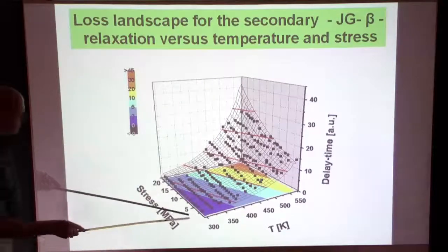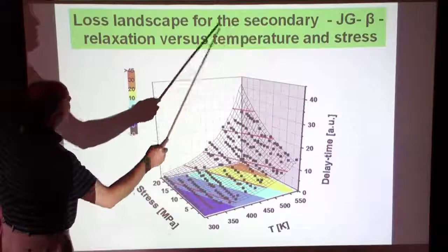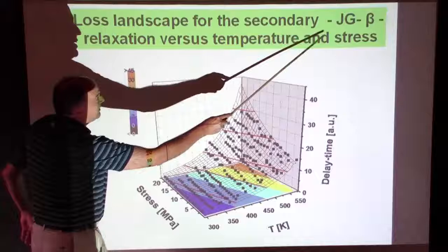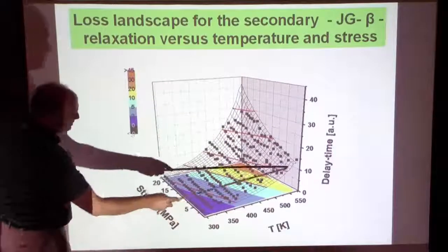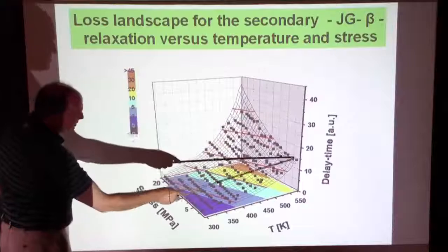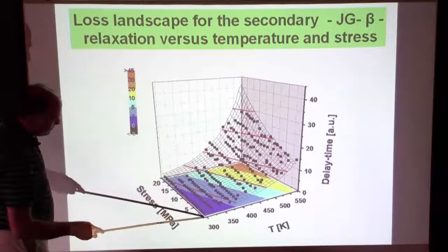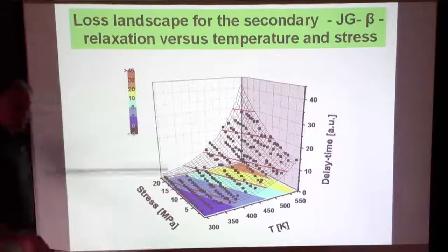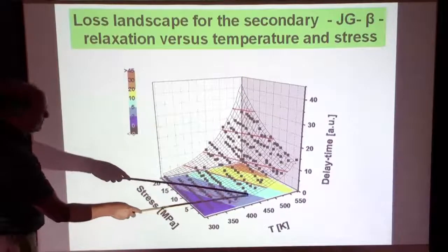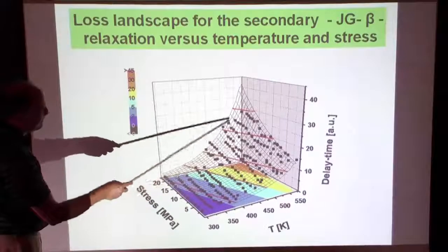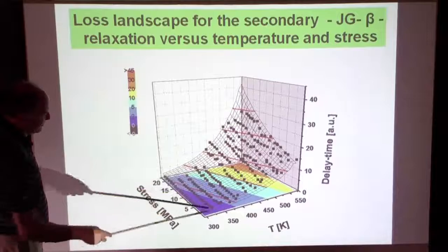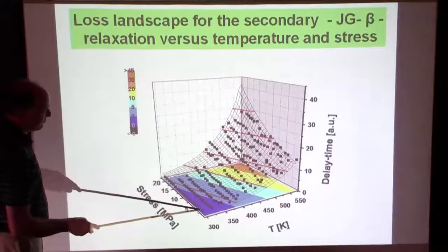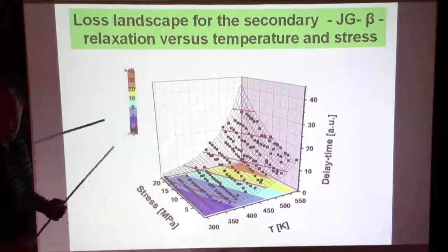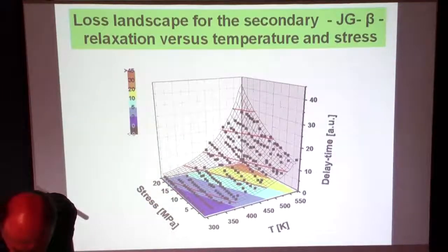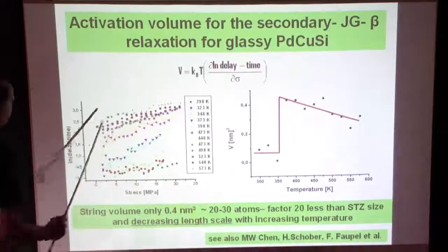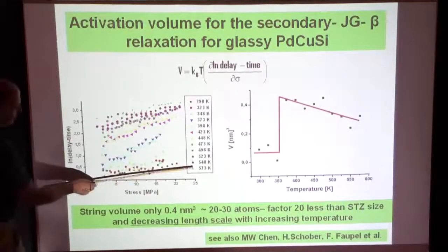So you can now measure the pure beta relaxation. Since everything is below Tg, we see only the secondary Goldstein mode here, and we measure the delay time. Delay time is something like the loss, versus temperature and minimal stress. If you now apply a certain stress on the sample at a fixed temperature, you can see how it looks in this three-dimensional picture of stress versus temperature, and these are the losses. If you go along a certain line at fixed temperature, the losses have a certain time scale, which is the delay time: the log loss versus stress at fixed temperature.